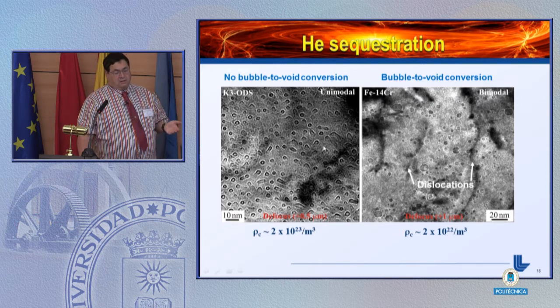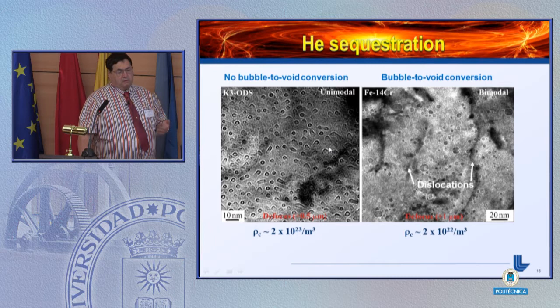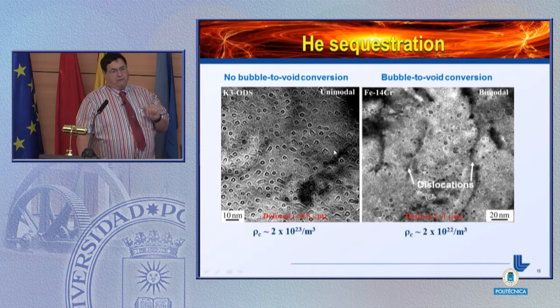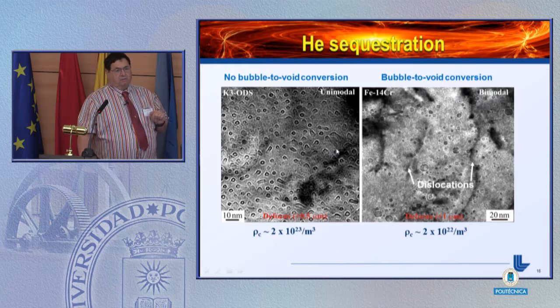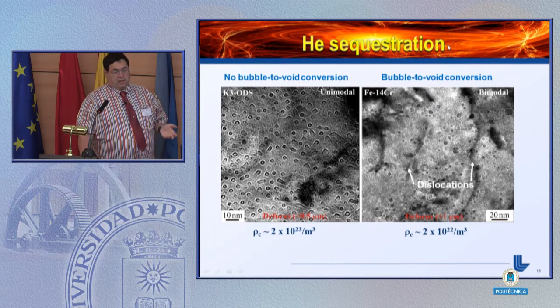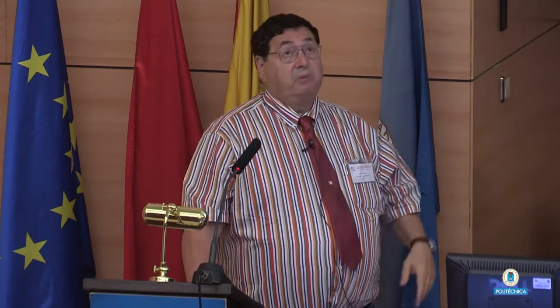So this is a technique. This says, let's put lots of small particles into a system and thereby stave off the possibility of rapid volumetric changes in the material. As I said, we simultaneously irradiated an iron-14 chrome specimen. This was about 40 dpa at 600 degrees C with a 40 atomic parts per million helium per dpa ratio. And here you see a bimodal distribution of cavities. These large cavities have made the transition to above the critical size, and the cavities are growing in an unconstrained way. The material is starting to swell.